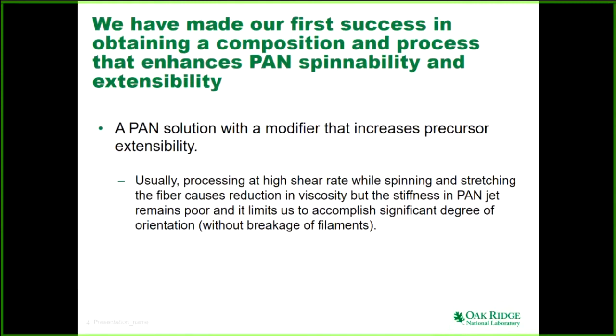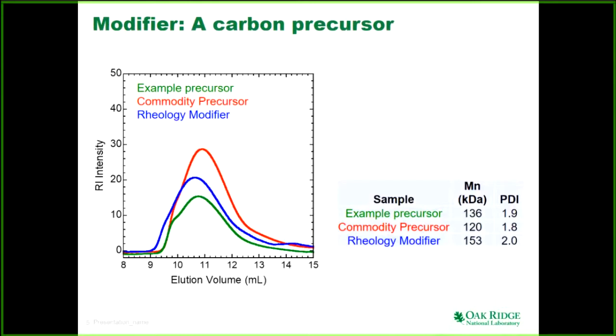So we made a composition using standard textile precursor, and we added a rheology modifier. When you add a rheology modifier, rheology means the study of deformation of fluid. When you are adding that modifier, you are increasing the material's extensibility significantly. So let us see what the characteristics of the rheology modifier are. Obviously, I didn't show here all the infrared as well as NMR spectra to identify the composition immediately. We can talk about that later on if you want.